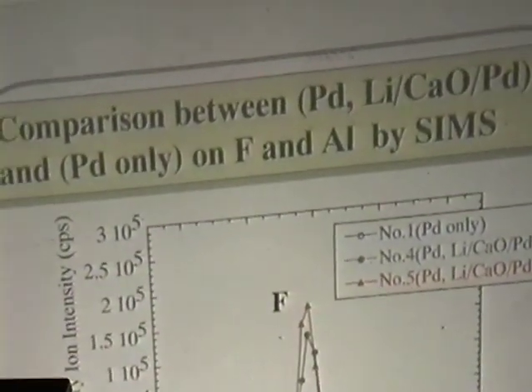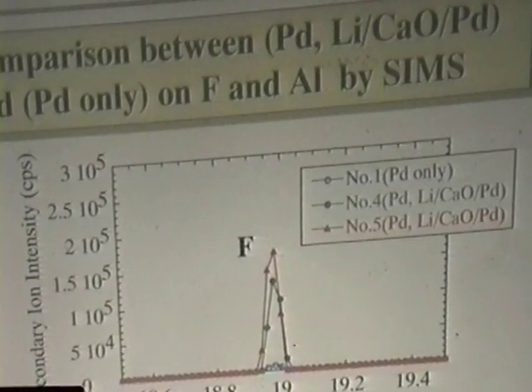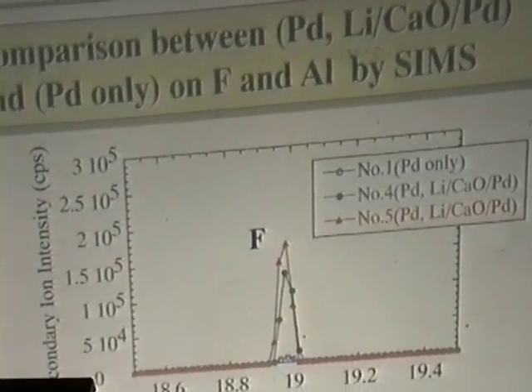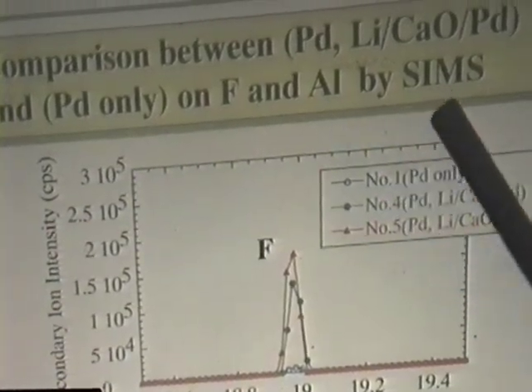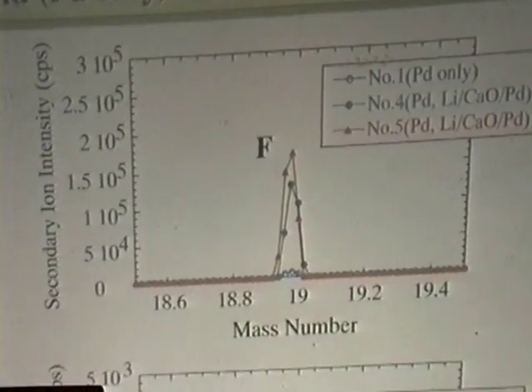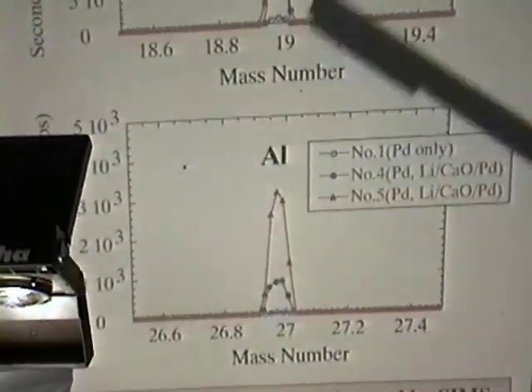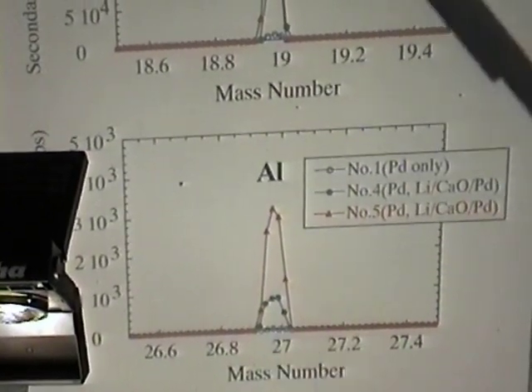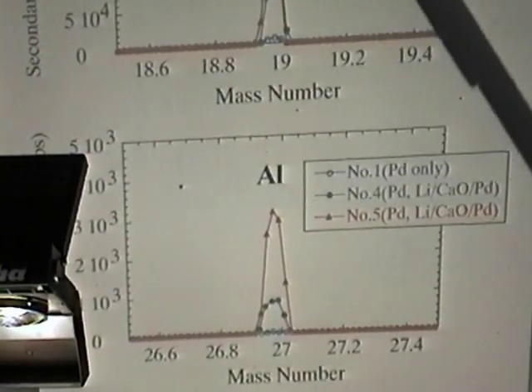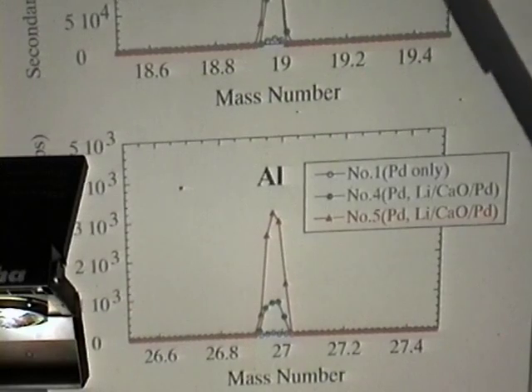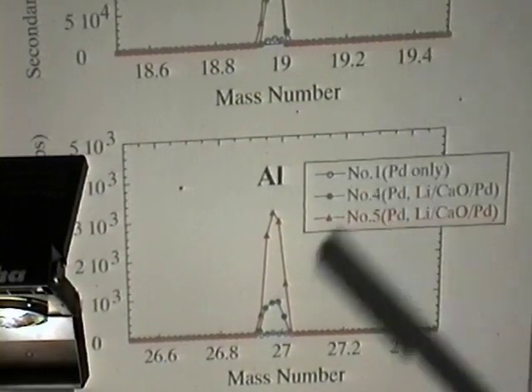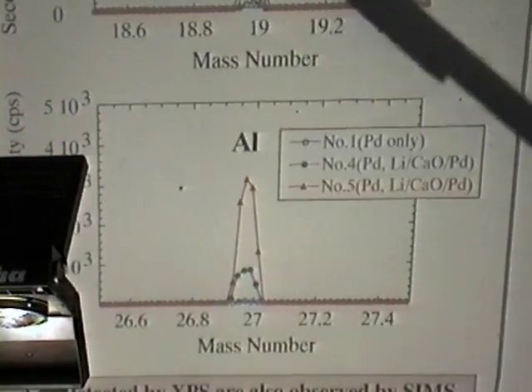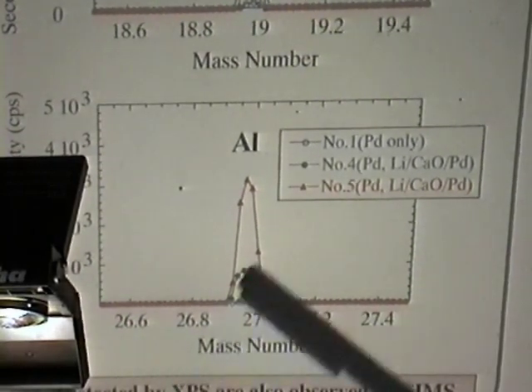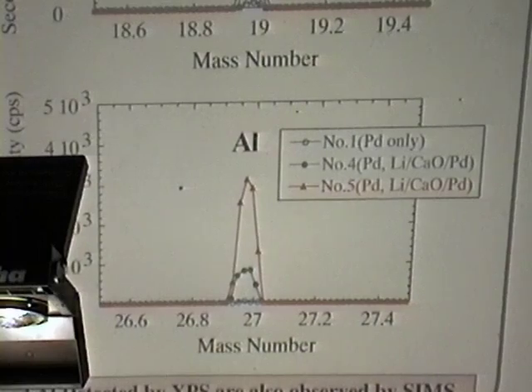This figure shows a comparison between lithium-doped multilayer palladium and palladium only on fluorine and aluminum by SIMS. The blue line is palladium only, and the green and red lines are attributed to lithium, palladium, calcium oxide samples. So we can see that fluorine and aluminum detected by XPS are also observed by SIMS.